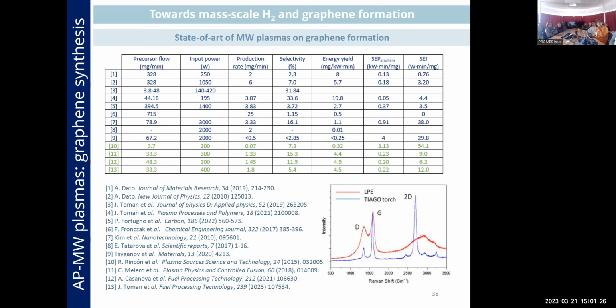In our case, the precursor decomposition is 100%, but we need to improve the selectivity for the formation of graphene as compared to, for example, this research. You see, they show a very high selectivity of the process. So we are working on that way to minimize the amount of energy that we will need for producing this graphene.